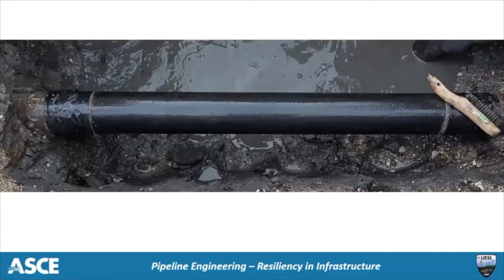Now the pipe has been thoroughly cleaned, which reveals that the oxidation that we saw was, in fact, superficial. After cleaning the pipe, we sound it using a geologist's pick or a welding hammer to see if there is evidence of graphitization, which would indicate corrosion pitting that would be penetrating into the pipe wall. In both excavations and all prior excavations we've conducted on this iconic pipeline, the corrosion has proven to be only superficial surface oxidation.